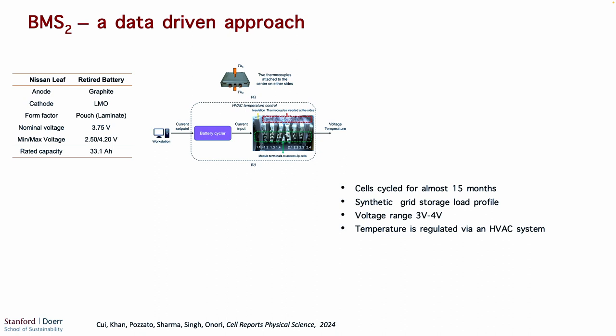So one of the characteristics of our aging campaign that we designed for them was to mimic typical grid storage load profiles, because we wanted data that was as close as possible to the real operation of the system. Another characteristic that we implemented was to derate the battery operation. Usually the voltage operation is between 2.5 and 4.2 volts. This is the voltage range that those batteries can withstand. In the case of second life, we reduced that to 3 to 4 volts. When you retire these batteries, you need to be a little bit gentle and mindful about how you stress them, because they won't perform as efficiently as they did in the first life.